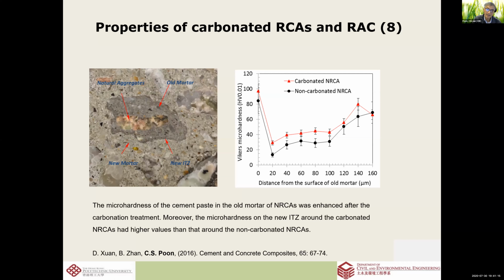Okay, and then this is for the carbonated one. This is a non-carbonated one. Then we immediately can see there's some improvement from the carbonation on the old mortar, because of the carbonation. But going deeper towards the new mortar, which is not carbonated, we can still see some improvement in what we call the ITZ.